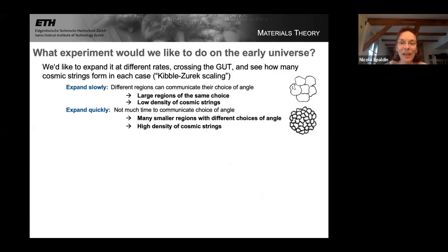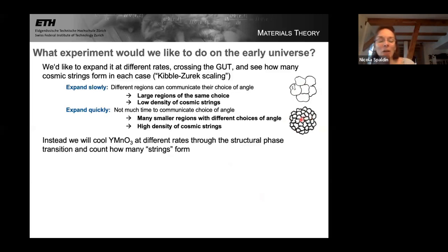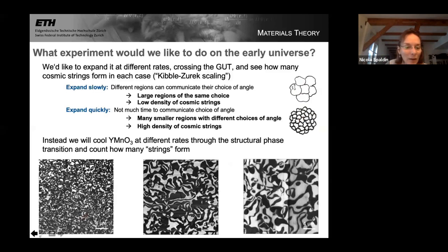Remember, if we expand slowly, we get large regions with the same angle and a small number of defects. If we expand quickly, we get small regions of the same angle and a large number of defects. So instead, we're going to cool yttrium manganite at different rates through the structural phase transition and count how many of the strings form. This is the thing I was mentioning earlier when we were discussing other possible systems for testing this Kibble-Zurek scaling.